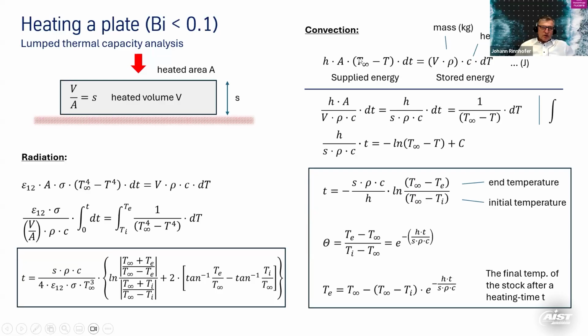So this is for convective conditions. The supplied energy from outside is a convective expression, so H times a temperature difference, a linear temperature difference. This is very much different from radiation heat transfer, because you are talking about T to the power of 4 when you talk about radiation. And so you have a slightly different expression and this awkward expression for the heating time in the end.